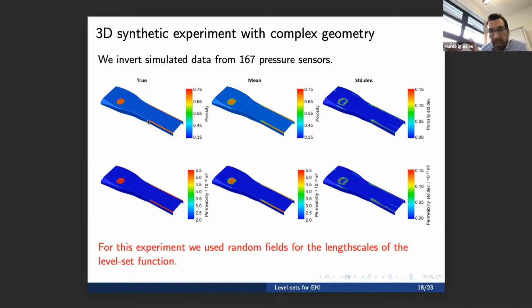But if you do this in the classical way that I showed before, where the length scales are constant, then the length scale in this direction will be relatively small to capture this circle, but it will not be able to capture something like this. So you need a length scale that is very high along this direction, only in this area, and relatively small in this area, in the circular defect. So we had to employ random fields for the length scale to have an additional level of parameterization to be able to capture this, provided that we have a lot of data.